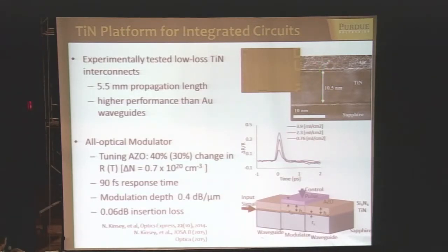It's 10 nanometers thick, and we demonstrated propagation length of 5.5 millimeters at 1.5 micron telecommunication wavelength, which is very comparable to what we obtained with gold.